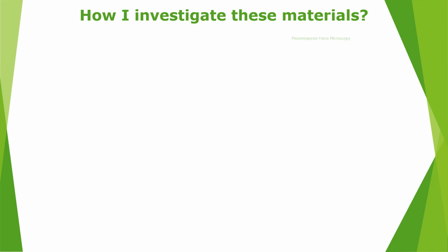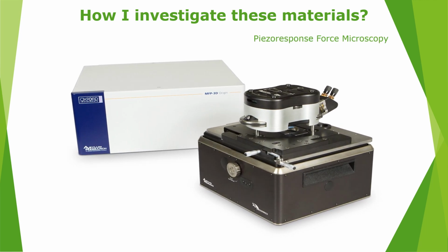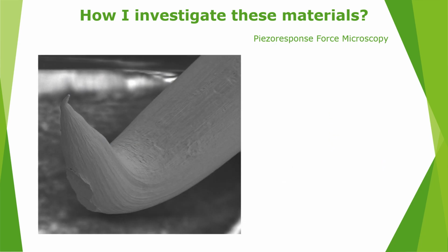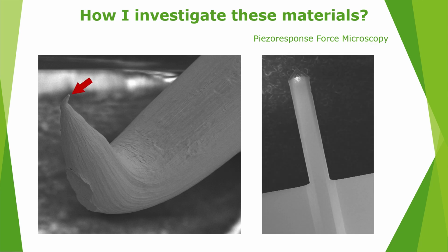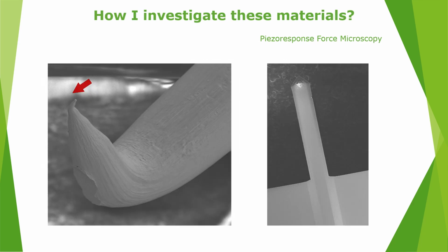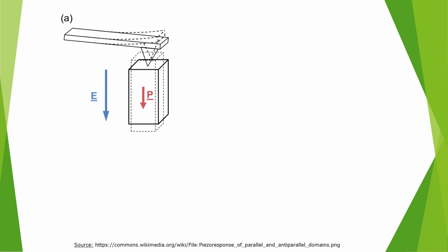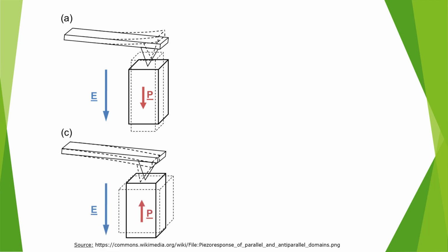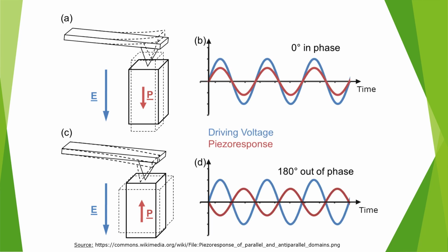I used a method called Piezoresponse force microscopy, conducted in an atomic force microscope. An atomic force microscope scans a surface with an extremely sharp tip that is located at the end of a cantilever. The tip apex has a radius of 30 nanometers, roughly 1,000th the size of a human hair. The tip is in permanent contact with the surface and driven with an AC bias, which leads to a local oscillation of the ferroelectric in the contact zone, due to the inverse piezoelectric effect. Since the domain response depends on the mutual orientation of the polarization and the electric field, a distinction can be made between differently oriented ferroelectric domains.